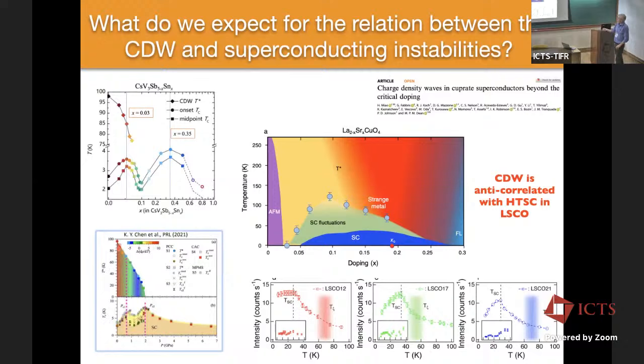And if the only information that I've got to go on in these systems is things like how the CDW and the superconducting transition behave as you perturb the system. And here, this is data that Stephen Wilson showed. It's his data, in which you're substituting in tin for antimony. So this is quite a big perturbation. You're actually changing the doping. But nonetheless, what you see is that the CDW goes down and the superconductivity goes up.